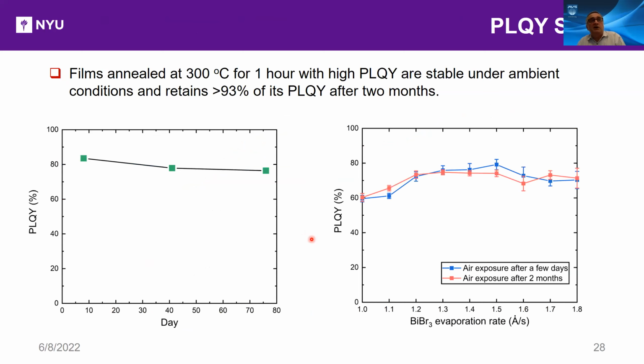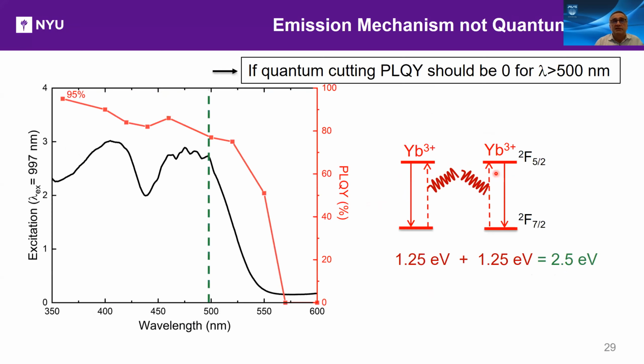Something about stability. So films annealed at 300 degrees centigrade for 1 hour are stable under ambient conditions and retain greater than 93% of their photoluminescence quantum yield. This is one of our champions after something like 70 days. And this is the same material, same data that I just showed you, the dependence of photoluminescence quantum yield on bismuth bromide, with all the data points taken after 2 months. And so you see that they're pretty consistently remaining high, and so they're stable in air.